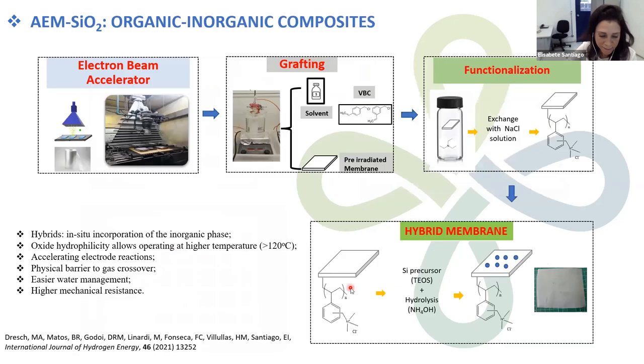So, we have expertise in organic-inorganic composites based on proton exchange membranes, such as Nafion and PBI. So we decided to expand our experience to AEM, producing the inorganic phase by in situ incorporation of silica, for example, into the resulting AEM obtained in our lab. Well, the idea is to prepare a hybrid. I mean that you have a resulting AEM membrane, and proceed with an in situ incorporation of the inorganic phase, for example, silica.